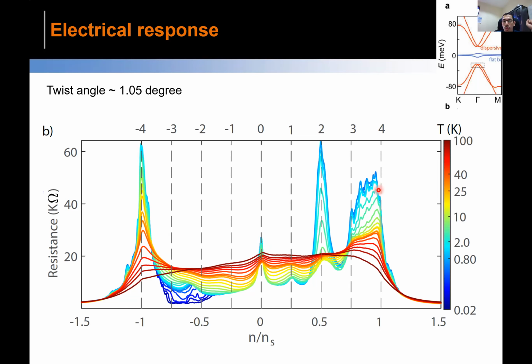So if I fill by 4 electrons per moiré cell, you see a large resistance. That is basically what happens: you have this flat band, but you are moving from the flat band to the higher, dispersive band. So you are crossing the gap between the flat and dispersive bands, and that is this peak. But before that, you have many other features at integer filling. For example, at 1 and 2, you see these peaks very nicely. These are the interaction physics I was talking about, particularly these two, which I was explaining in terms of the Mott peak and so on.